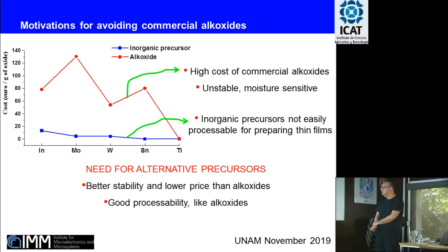And they also have some other important advantages. For instance, the alkoxides are unstable, they are moisture sensitive, you have to handle them in a glove box, and they are very pricey. But the inorganic precursors also have another disadvantage, which is that it is not easy to process these solutions to prepare thin films. We have problems of inhomogeneity, of adhesion of the film to the substrate, and so both classes of precursors have some advantages and some disadvantages.